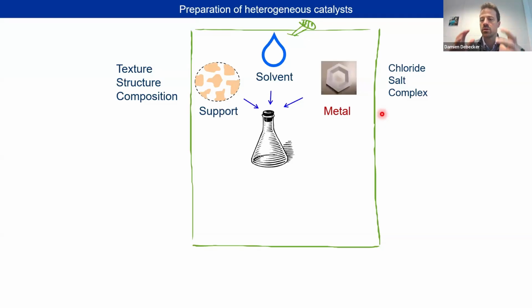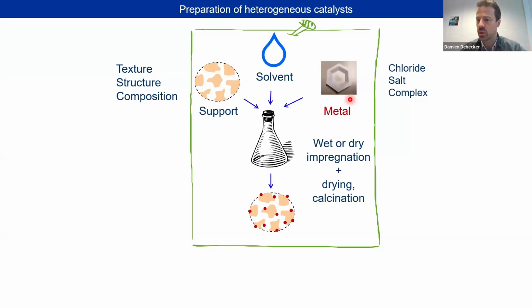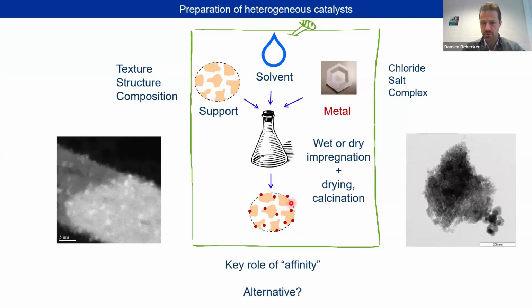We don't use that metal or that metal oxide alone. As such, we will usually support it, disperse it onto another material that is called the support. So you would take a support that has the right texture, structure, composition. You would mix it in the presence of a solvent with a precursor of the metal that you need for your reaction, be it platinum, ruthenium, molybdenum oxide, or these kind of things. And after impregnation, what we call impregnation, there are steps of drying and calcination, and you end up with your catalyst. So that's a very general scheme, and in some cases, it works very well.